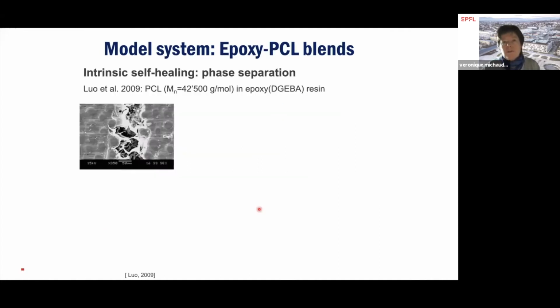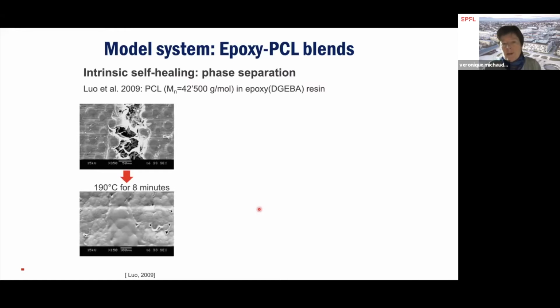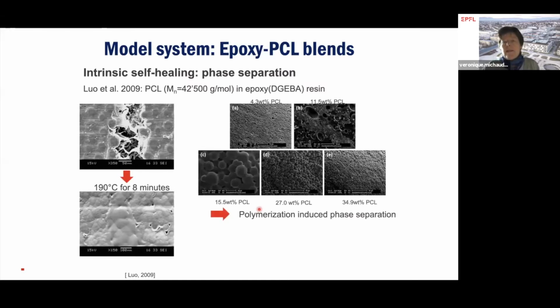There are model systems that exist in the literature, and we got inspired from a paper that was published about 10 years ago by Luo et al. On intrinsic self-healing with phase-separated matrices using a PCL in an epoxy, a traditional DGEBA resin. He showed that by heating at 190 degrees for 8 minutes, you got complete healing, and that, in fact, it depended a lot on the microstructure, which itself is a function of the volume fraction of PCL, or the mass fraction of PCL in the blend.